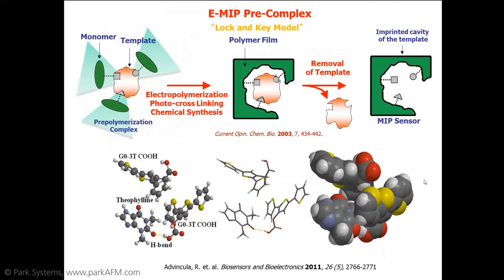The thing that we add in terms of increasing the efficacy of these systems is basically modeling it in terms of non-covalent interactions. Non-covalent interactions means that we optimize the ratio of the monomers that are used for a particular analyte. In this case, you can see a 2-to-1 ratio that has been optimized using semi-empirical ab initio methods or calculations to generate the most stable conformation as well as the most stable pairing for the analyte and the monomer.